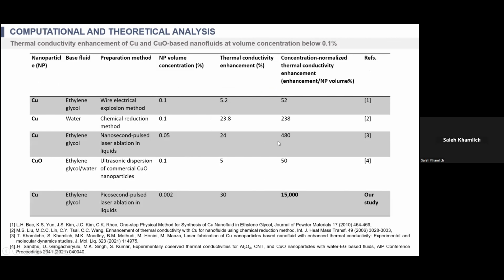So in this study, compared with other studies, we found an enhancement. This is a ratio, the enhancement normalized by concentration: the thermal conductivity enhancement, which is 30%, divided by the concentration, gives 15,000 for this study. Other studies used higher volume fractions. So these are their enhancements. These studies mainly used copper because we're interested in copper in this study. So in our study, we found that the picosecond green laser gives higher enhancement at very low concentration.